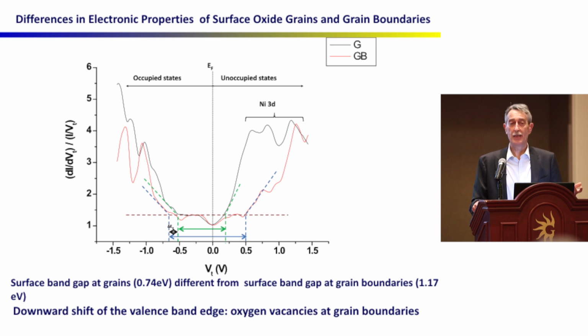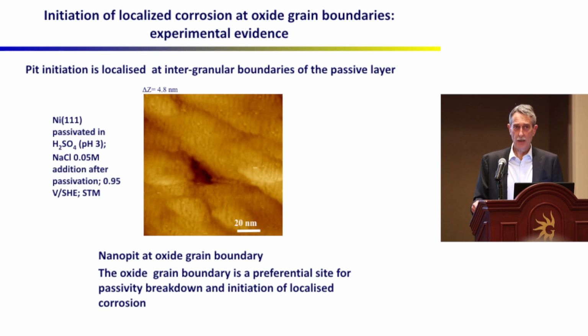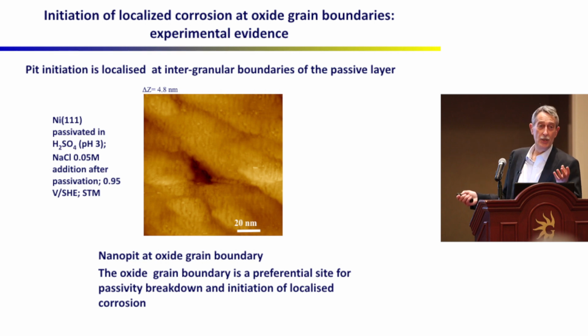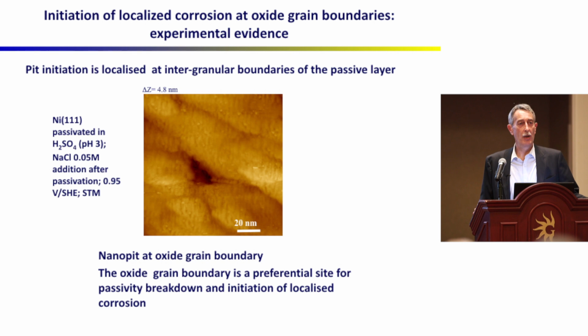And now, using the STM, we can look at where pits initiate by imaging the surface. If you do that, this is what you observe. This is a nano pit. So it's really the initiation stage on a passivated nickel surface. You can clearly see the grains of the oxide. The substrate is a single crystal, so there is no grain boundary in the metal, but you have the grains, you have the 3 grains here. This is a triple point, and that's where the pit initiates.